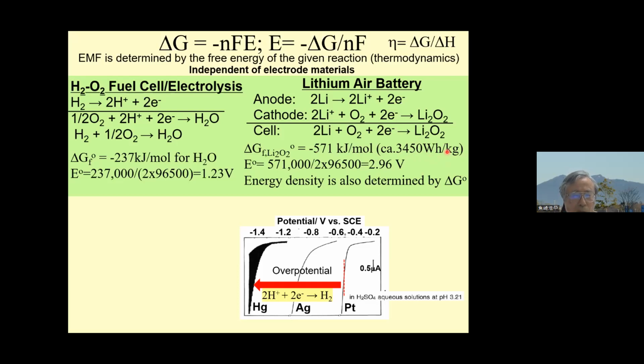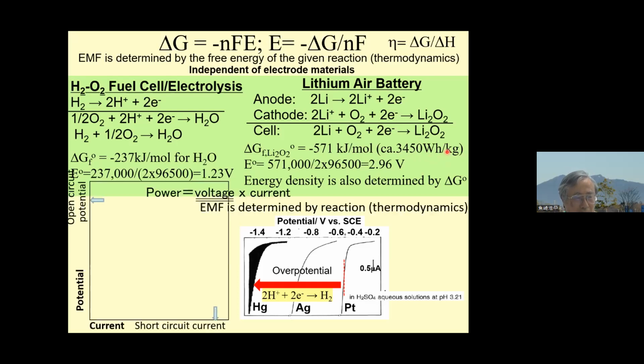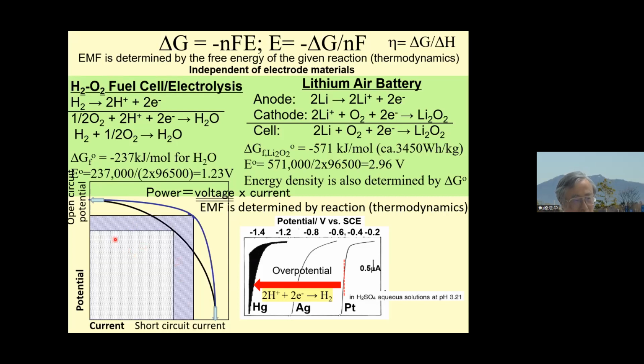So thermodynamics tells you what we can do with these battery systems, but again, in the case of a battery or fuel cell, we need not only voltage, but power. Power means voltage multiplied by current. So electromotive force can be determined by the reaction, but current is not. In this situation, this square gives you the power, and maximum power is like this. In other cases, this is a very bad situation: when we run the current, the potential drops very quickly. Those depend on the current, which is the electron flux, which means reaction rate. So the higher the reaction rate, the better the performance. So the potential is thermodynamic, but current is not thermodynamic, it is reaction dynamics.